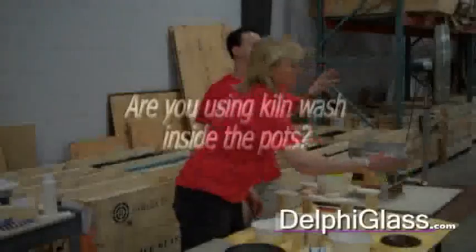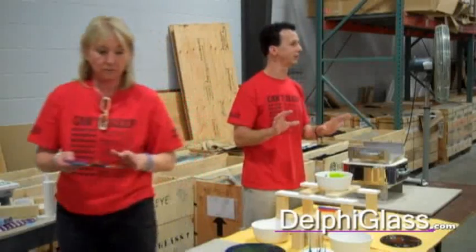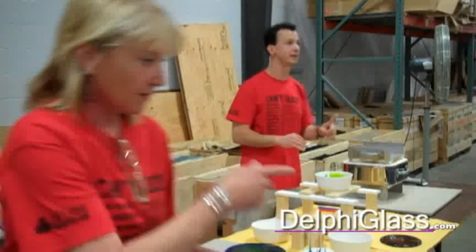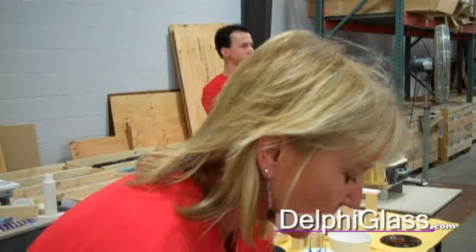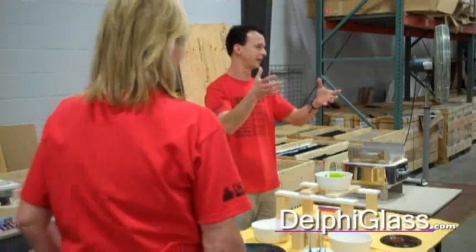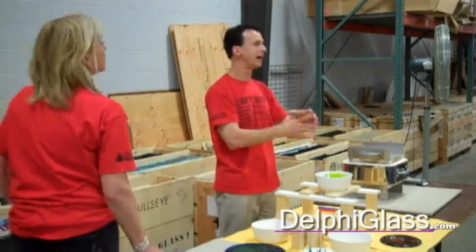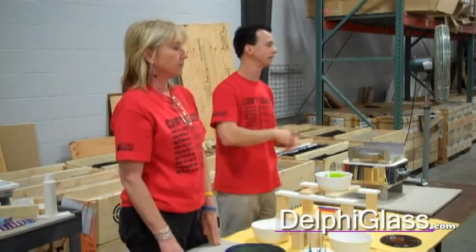We're not using kiln wash on the inside of the pots, we don't use any kiln wash on them. The reason is that as the glass drips and goes through the hole, it will pull the kiln wash with it and drag it down into your pot melt, and then you get all that white cloudiness from the kiln wash.